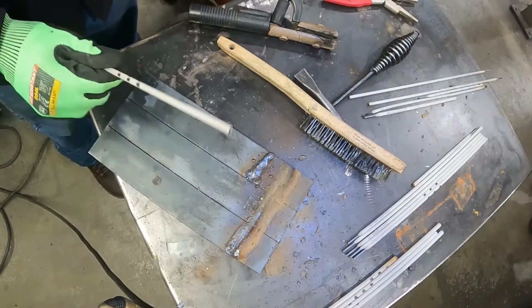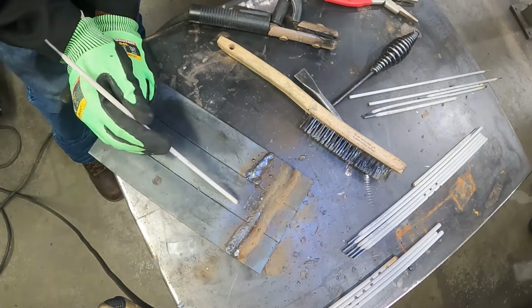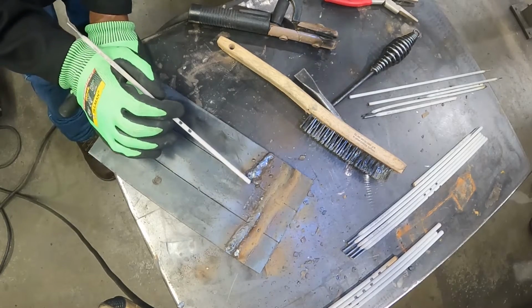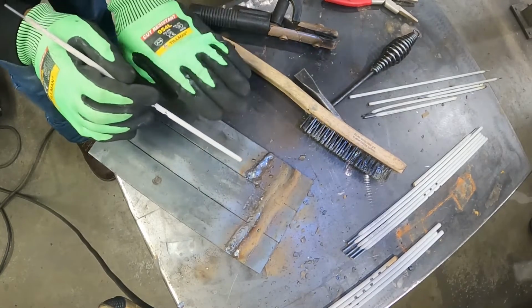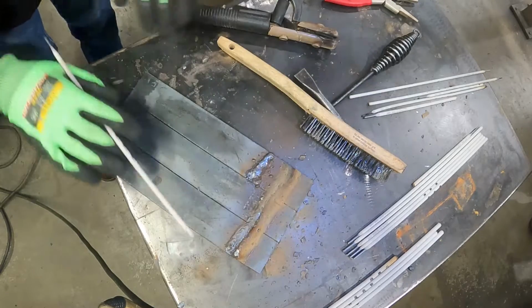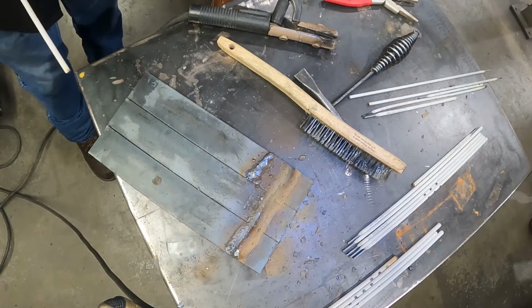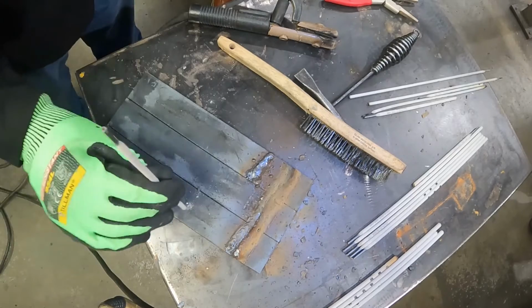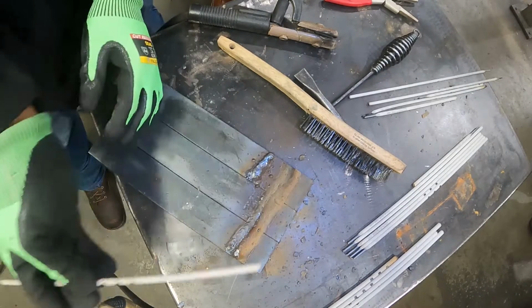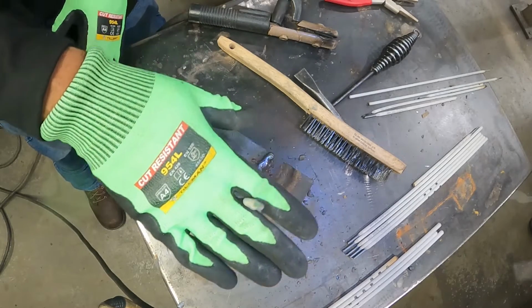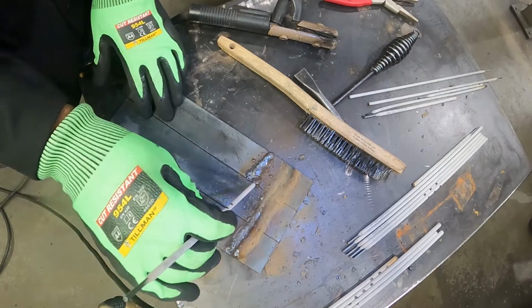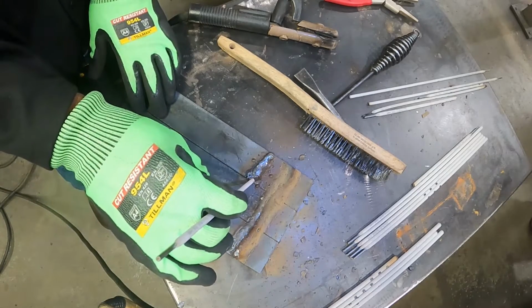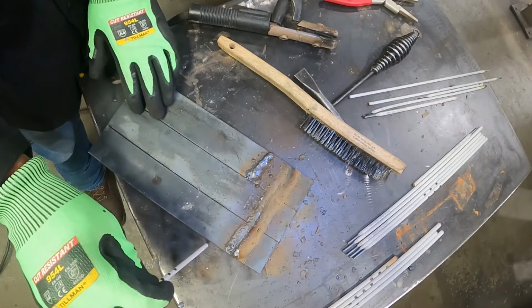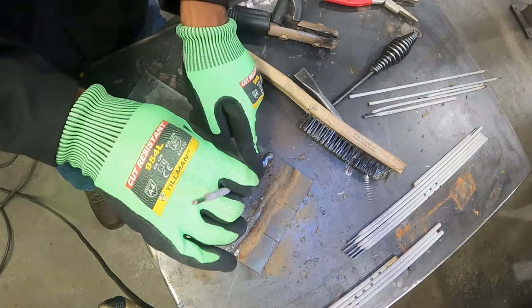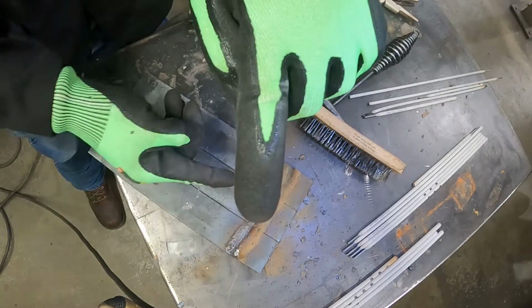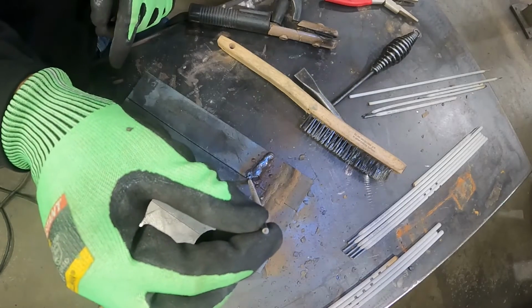Okay? And then what you also did, you came in with a real steep work angle. Okay, your angle was way down here like this, right? So really all the pressure of the rod is pushing and spattering out. And you had a little bit of long arc in there, right? Y'all observed that too? All right, so let's talk about it. When you strike the rod, you want the rod to be perpendicular to the part with a slight drag. Okay, so it's gonna be like this, strike, go back over where you just struck, and then start depositing weld. Okay? But notice, the rod is perpendicular to the part with a slight travel angle. Okay, about 10 degrees. Okay?